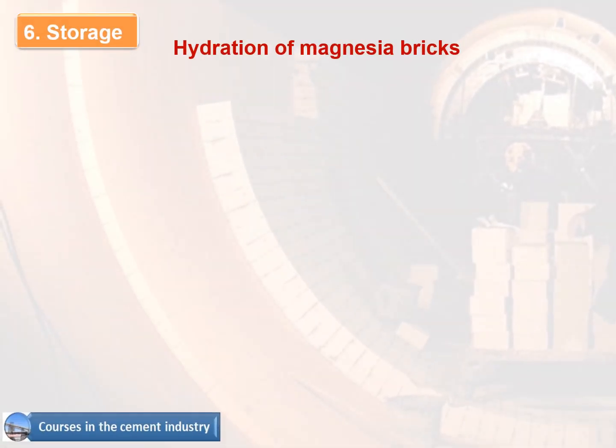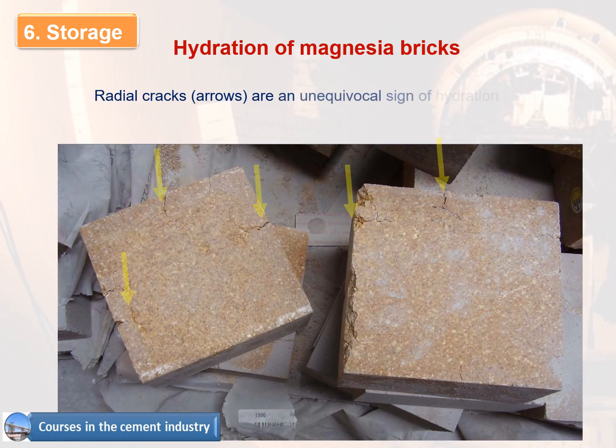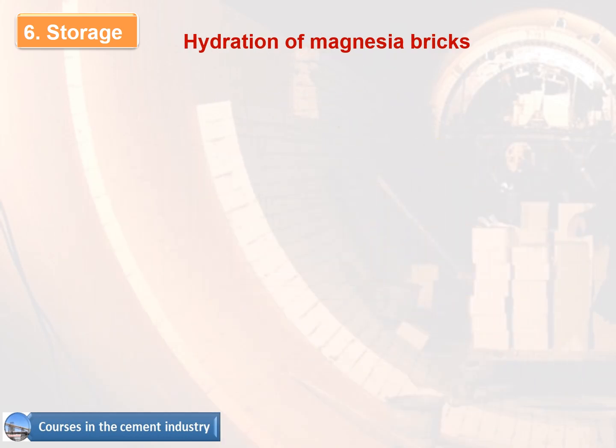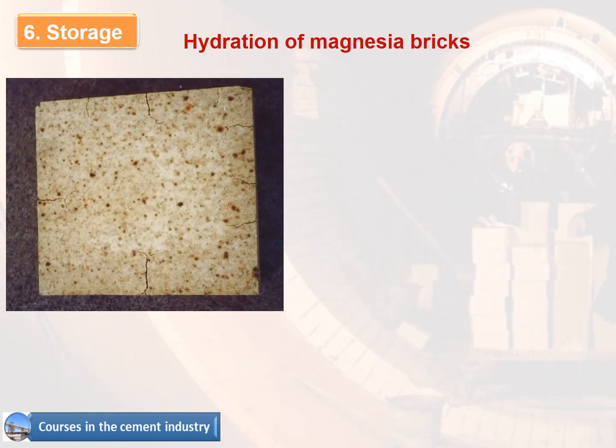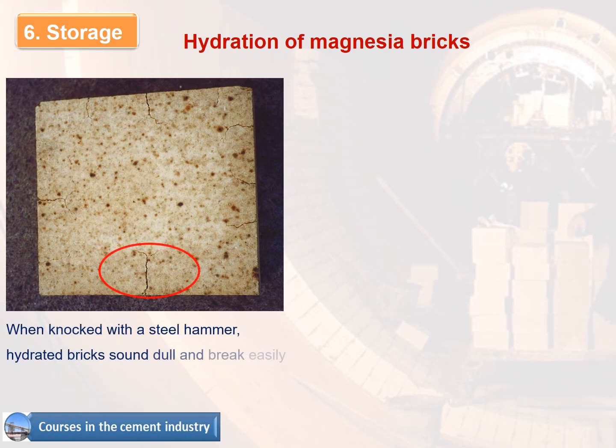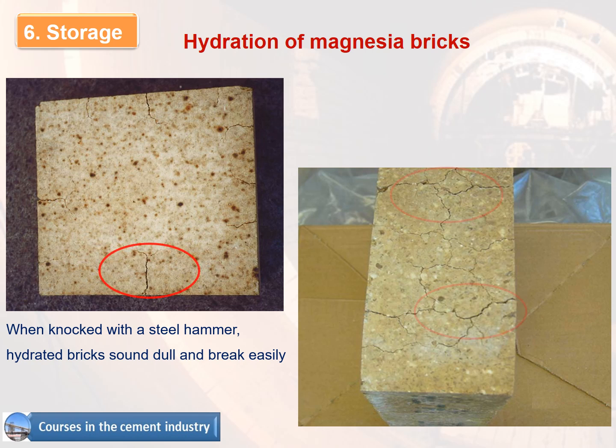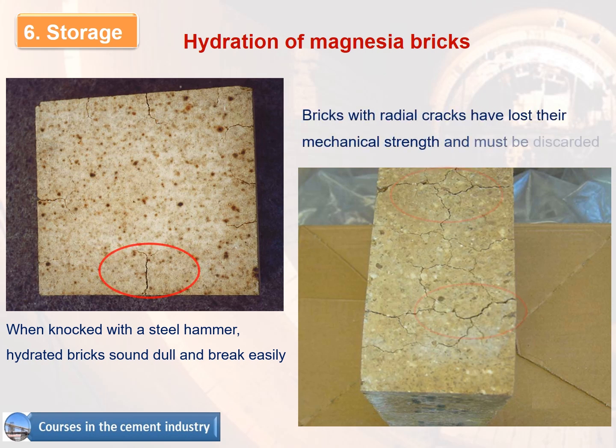Hydration of magnesia bricks. Radial cracks, arrows, in the figure are an unequivocal sign of hydration. Hydrated bricks cannot be used anymore. In this figure, when knocked with a steel hammer, hydrated bricks sound dull and break easily. In this figure, bricks with radial cracks have lost their mechanical strength and must be discarded.